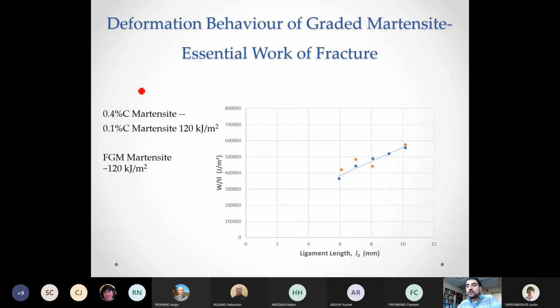And next, we tried the material which is functionally graded, the one that has 0.4% carbon at the center and 0.1% at the surface. And amazingly, the points are very similar to the behavior we get. There is more scatter, but the points are more or less similar to what we have with the 0.1% carbon. So it wasn't an average between 0.1 and 0.4. It was actually very similar to what we got with the 0.1% material, which is a remarkable improvement in terms of the toughness, while keeping the strength of this graded material much higher than the strength of the 0.1% carbon material. And if we do additional heat treatments and grain refinement and so on, we can even get a material which has even higher toughness.